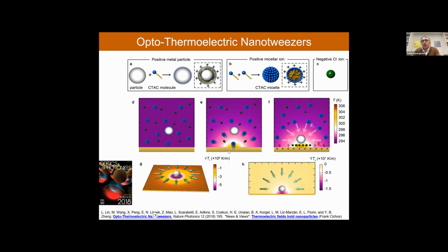I see. But would you assume that it's basically homogeneous, or do you go to one of the nanoparticles? It's a network, so it's a random distribution. But the particle size is much smaller, so at one laser beam location, you have several particles. The reason we want them separate is because we want to reduce the thermal conductivity, so that we have a localized heating source. If we use a continuous thin film, the heat will dissipate, so our trapping will not be confined. Yes, got it.